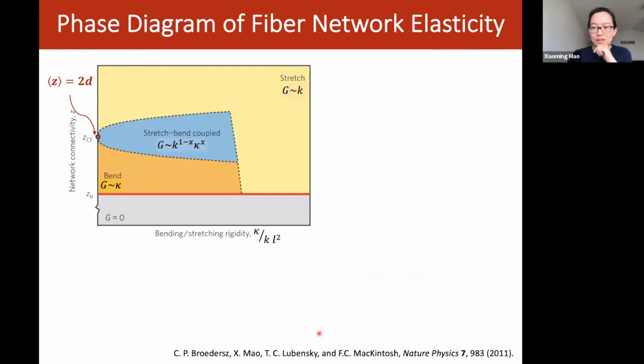Okay, so this was basically the idea of this work we have done a while ago, trying to understand the linear elasticity phase diagram for fiber networks. By studying some diluted lattice models, we extracted a phase diagram like this, where the horizontal axis is the bending versus stretching stiffness for each of the fibers, and the vertical axis is the connectivity of the network in terms of the coordination number.